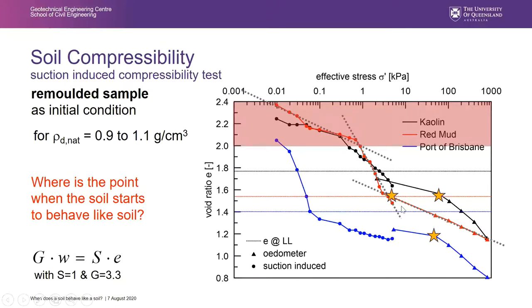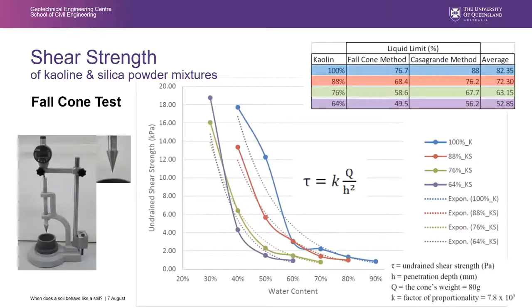And as you see, only in the case of the red mud does it correspond to the liquid limit. In the other cases, the water contents are higher, or let's say the corresponding density state is lower. We can do a similar consideration also for the shear strength. So when do we have really an increase in the shear strength? I don't have any results here with the tailings material, but with substitute materials, which are a mixture of kaolin and silica powder. Here there are the different mixtures. So in one case, blue is 100% kaolin, 88% kaolin, and correspondingly then 12% silica powder, and so on.